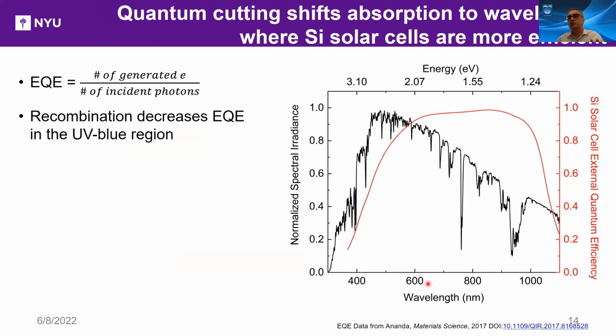There are other benefits to taking the blue photons to the near infrared, and that has to do with the external quantum efficiency of the silicon solar cells, or any solar cell for that matter. External quantum efficiency is the number of generated charges per number of incident photons. And here I show both the normalized spectral irradiance for the sun, as well as the external quantum efficiency of a typical silicon solar cell taken from this reference.